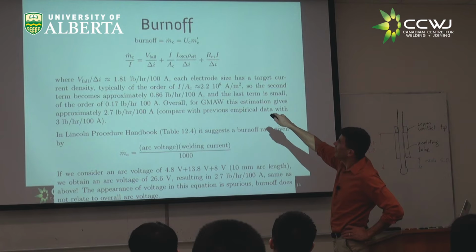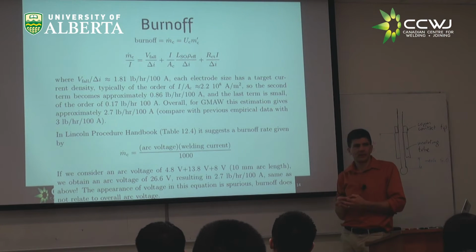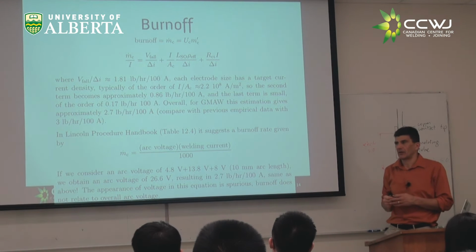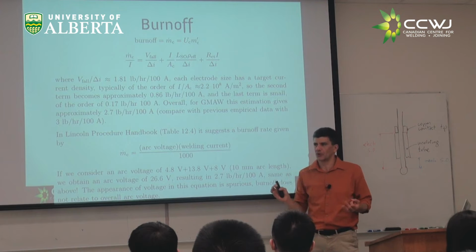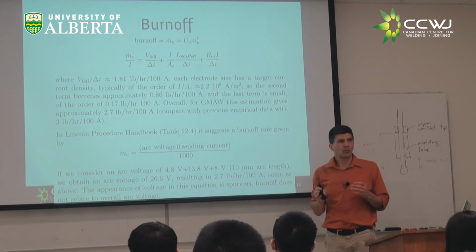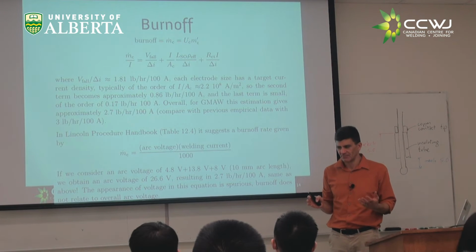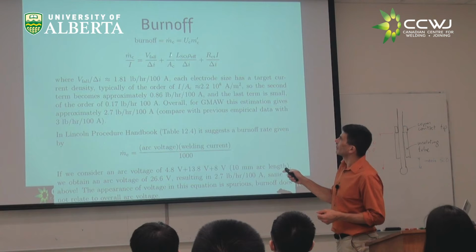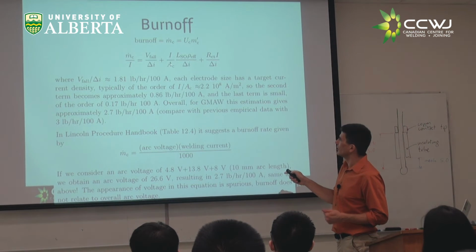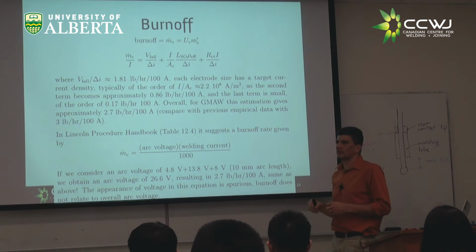And here we have current divided by the cross-section of your wire. Okay, that is not constant. For a given wire, you can have any current you want. Now, what happens, and this is something for which I need to ask the practitioners, but in practice, this current per cross-sectional area of the wire is more or less 2.2 times 10 to the 8.